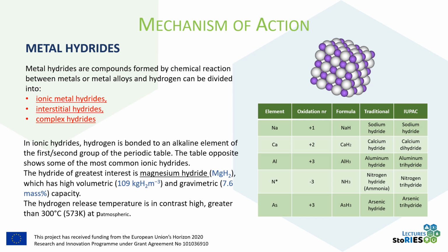These properties make magnesium hydride an attractive candidate for hydrogen storage applications. However, it is important to note that the temperature required for hydrogen release from magnesium hydride is relatively high compared to others, exceeding 300 degrees Celsius, that's 573 Kelvin, at atmospheric pressure. This factor presents challenges that must be addressed when considering the practical implementation of magnesium hydride in hydrogen storage systems. As we were saying, there are always advantages and disadvantages.